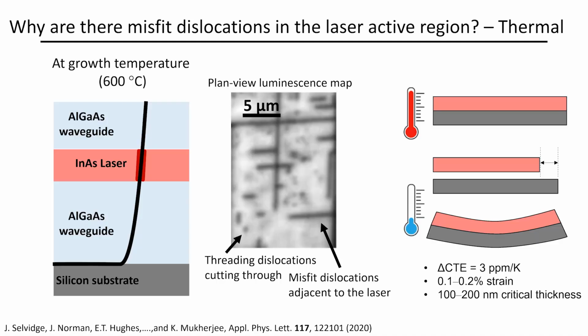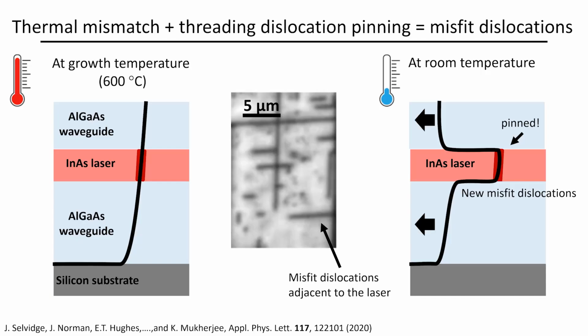So there was a bigger problem, and we said, well, let's go back to our old friend thermal expansion. Is it possible that what's actually happening is that all of those black lines that you see are being formed not because of the mismatch in crystal structure, but because of the cool down process? So we had a hypothesis. Indium, we had shown, was so effective at pinning dislocations. Maybe our laser is a giant pinner of dislocations, our entire laser itself. So that's our hypothesis. We said, oh, the laser actually blocks the dislocation from moving during thermal expansion cool down, and it forms these very unusual hairpin structures.